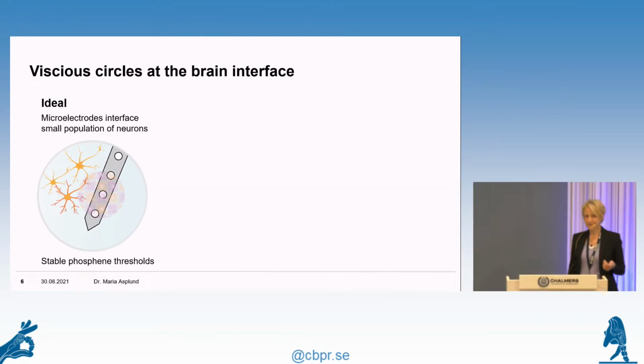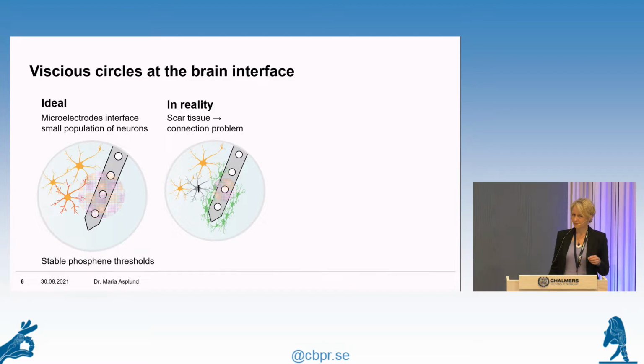So, why is this? Well, ideally we would like to make extremely small electrodes, so much smaller than the Utah electrode array. And we would like to have these electrodes in intimate contact with neurons, so we can stimulate only a few neurons at a time, which means that the threshold current we need to inject to trigger a phosphene remains low. In reality, scarring comes in, meaning we will have inflammation, we will have a glial scar forming, which is an insulating capsule. Some neurons close to the device will die because of the neurotoxic environment.